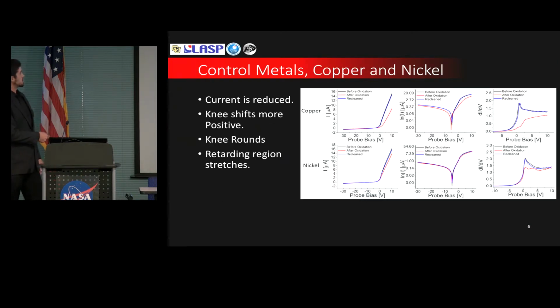You see here that the black and blue, that's the before, and the recleaned, those overlay very nicely in all these cases. The red is after oxidation. You can see here the copper. This shows the most exaggerated effect due to oxidation, and is what we talk about when we characterize the effect of oxidation on a Langmuir probe.